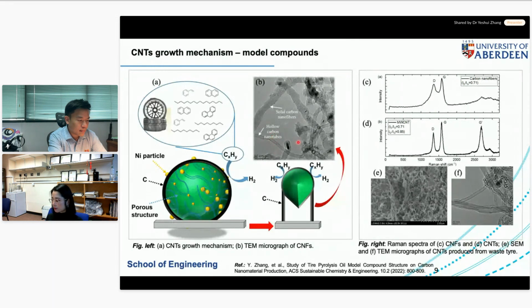Why sometimes, if you look at this figure B on the left-hand side, we have this solid structure of carbon nanofibers rather than the hollow structure of carbon nanotubes. And in the worst case, we even have amorphous carbon formed on the catalyst surface that will only degrade the catalyst without any value, I mean profits, from producing the amorphous carbon. So I want to find out the synthetic growth mechanism. In that case, I could really control the process and maximize the production of the synthesis and also try to increase the quality. Obviously, we want the synthesis to be formed more homogeneous.